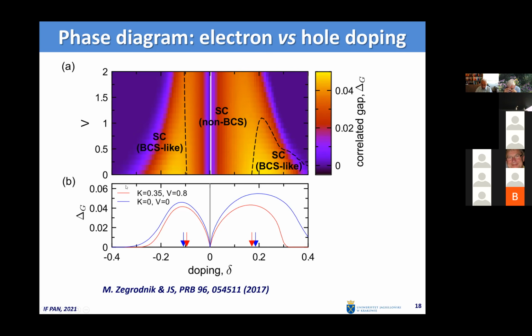It turns out if you go beyond mean field, this parameter of correlated hopping does not influence superconductivity much. Really, correlations plus exchange is the thing, because these are the main curves. This difference is, as you can see, smaller. And with the intersite Coulomb interaction, the upper critical concentration for disappearance of superconductivity is not 0.42, which is wrong, but closer to 0.3 or even lower, depending on how big is the intersite Coulomb interaction or correlated hopping term.